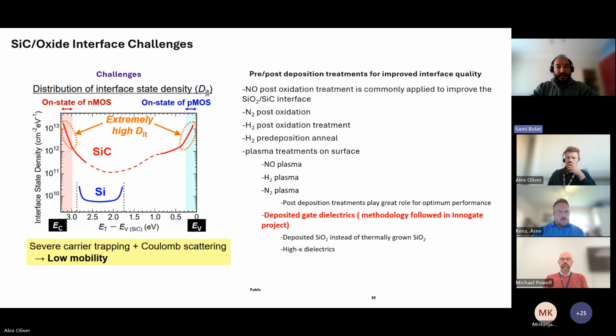So, of course, the industry doesn't just adopt the thermal oxide directly and that's it. We had to do quite some tweaks across the decades. And today, what is commonly applied to improve the interface is nitric oxide post-oxidation treatment. Then, of course, there are several studies at the academic as well as industrial level using high temperature post-oxidation annealing to fix the interface density. The hydrogen post-oxidation treatment is shown to be quite an effective method, with a question mark on the stability of the device. The pre-deposition anneal with hydrogen is known to cure the surface roughness of silicon carbide when it is done at an appropriate temperature. Then, as Michael was also hinting, plasma treatments on the surface can greatly change the behavior of the device for silicon carbide as well.